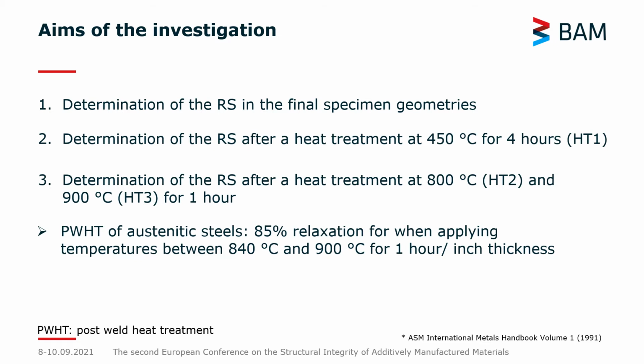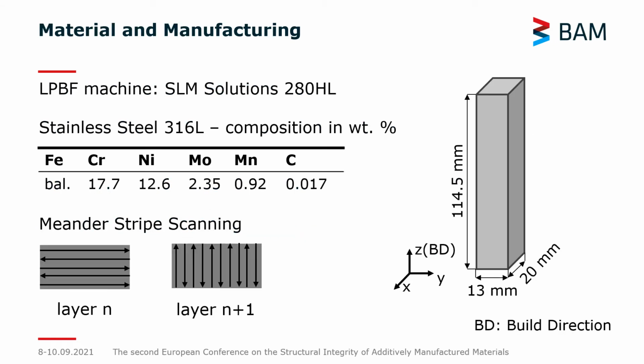We manufactured our specimens on a SLM Solutions 280HL LPBF machine using gas atomized spherical stainless steel 316L powder. You can see the composition in weight percent over here. A meander stripe scanning strategy was applied, thereby the scanning vectors were aligned with the geometry. Also, we applied a rotation by 90 degrees between each subsequent layer.